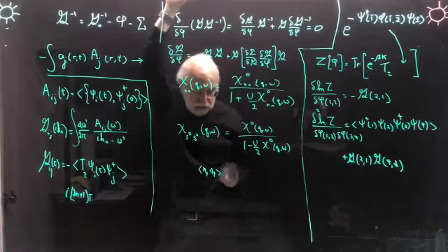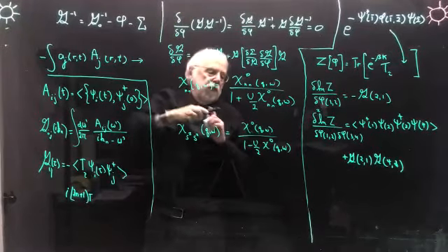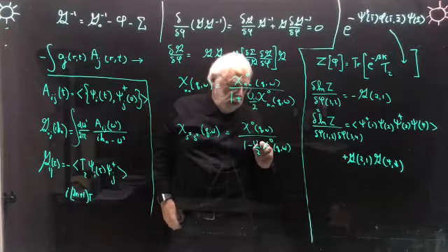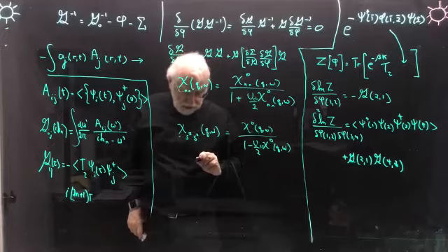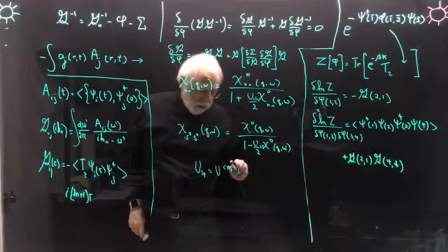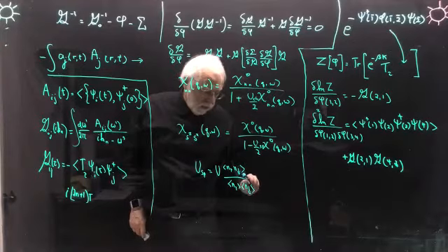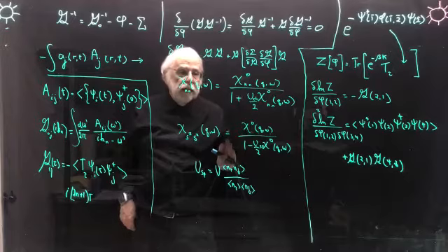So we fix that by having U charge and U spin that are determined in such a way that the Pauli principle is satisfied, and that U spin is equal to U times n up and down divided by n up times n down, using the charge and spin sum rules.